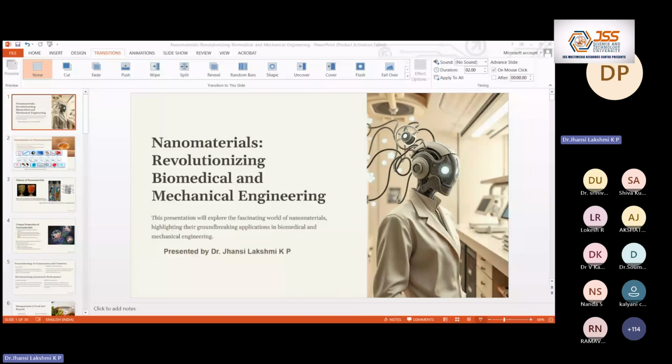They found that two nanoparticles, silver and gold, in the ratio of 7:3, were mixed with 10% copper and dispersed in the glass matrix to get this dichroism.